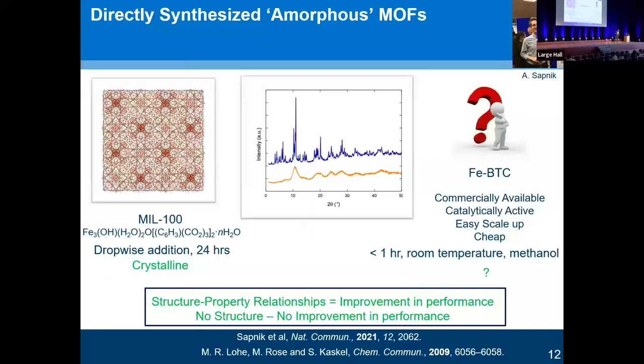The other thing we're really interested in is not only killing beautiful systems, right? We're not just MOF killers, we also make them. And so Adam has looked at this beautiful MIL-100 system. Unfortunately, as beautiful as it is, you have to form it over about 24 hours of dropwise addition, right? So that scale-up could be a problem for industry, but beautiful structure, right? Everyone's happy, great, brilliant. Gives rise to a Bragg diffraction pattern.